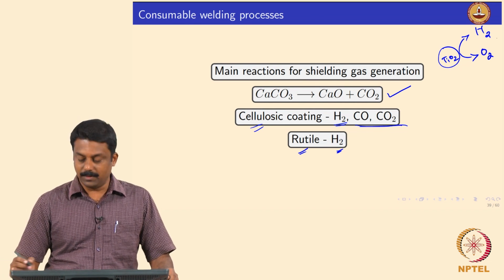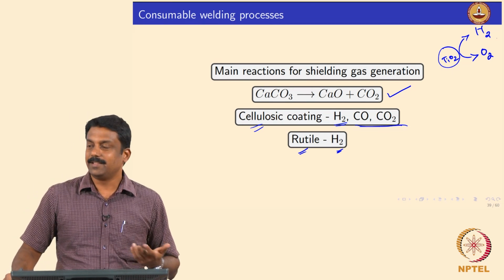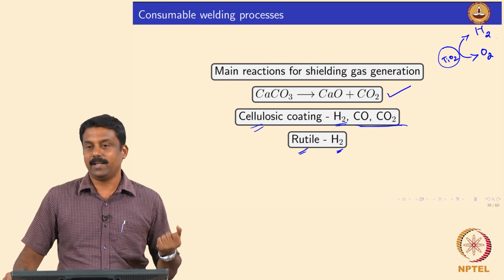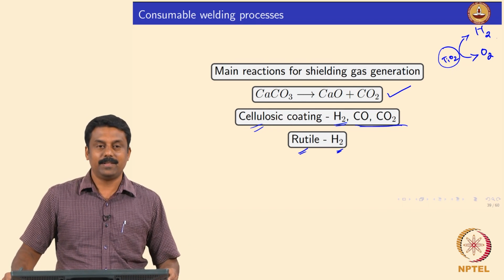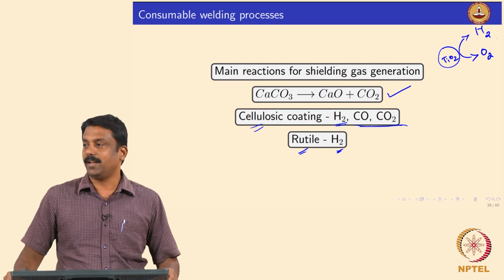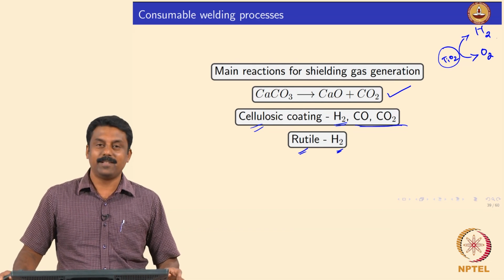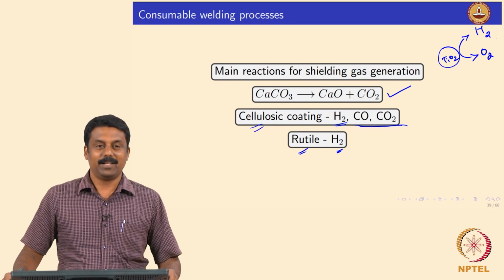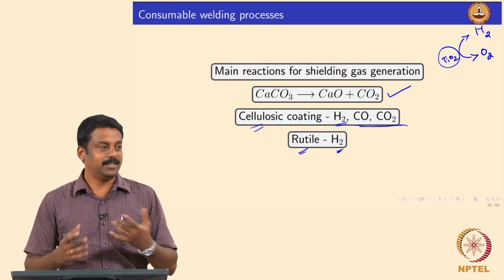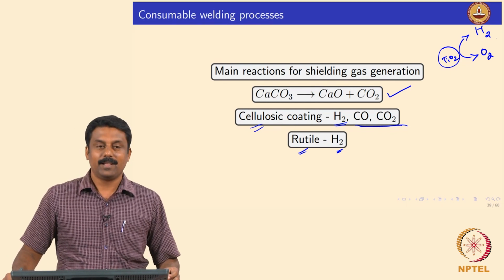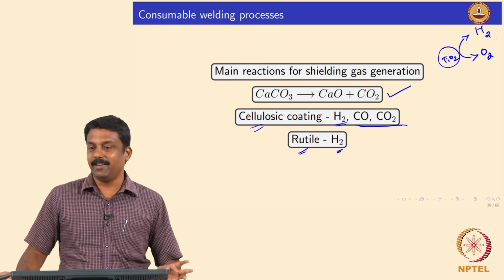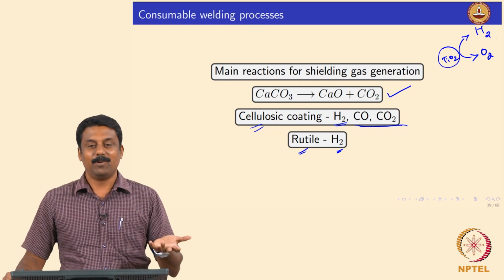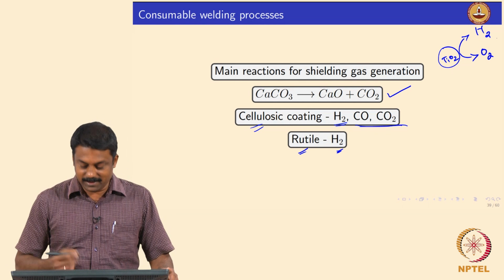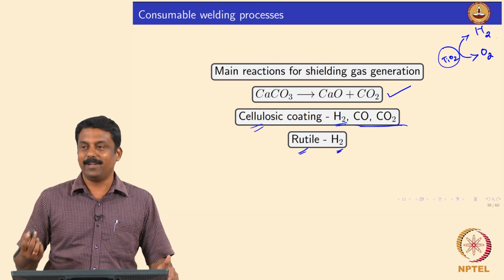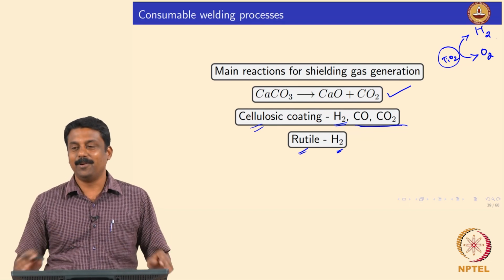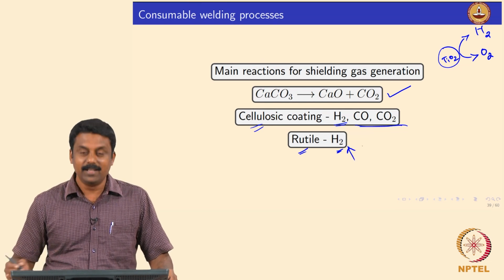Okay. So, titanium oxide nowadays people explore left and right, generate the nano titanium oxide, use it as a photocatalytic agent to generate hydrogen. So, hydrogen fuel cells, you may see they use nano titanium oxide rutile, and we use it in welding also, but we do not really call ourselves nano guys, because ultimately when titanium oxide is added in the flux, it would disintegrate, it becomes nano titanium oxide, and we generate hydrogen, right. That is why I call welding, welding does everything. Okay. So, we do steel making, we also work on hydrogen generation, right. But it has been done for several years, and we do not claim ourselves as advanced researchers. So, we play low level, okay, but still we use the titanium oxide to generate hydrogen for shielding, right.